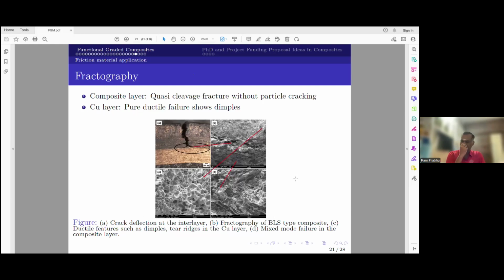Fractography. This is a very essential one. This is the cross section: this is a copper layer, this is your composite layer. Look at it. When any crack forms in the composite layer, it is very drastic and very sudden. You can see it propagates vertically very fast. The moment it encounters the soft copper layer, you see branching of the cracks. If you expand that branching, you can see it propagates at a 45-degree angle. So if you look closely here, the crack propagates at 45 degrees to the loading direction.